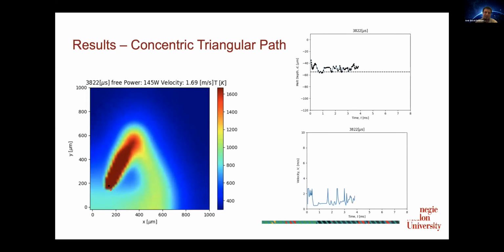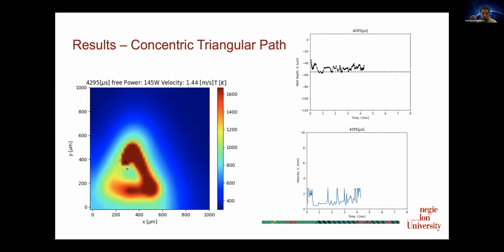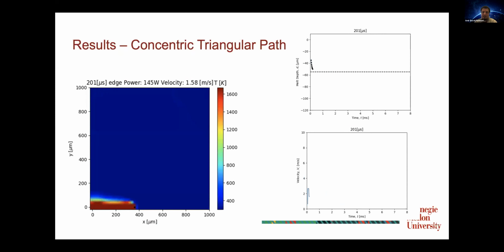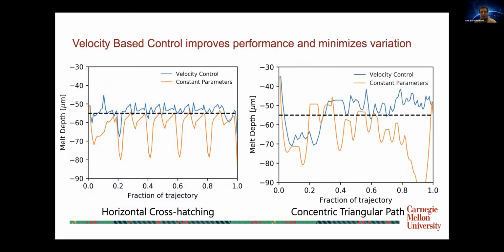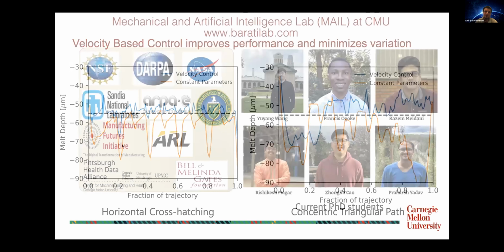Especially in the middle, there's a huge accumulation of heat. So turning off that laser is very important. Here you can see there is a huge difference between when you are controlling the velocity and if you are using a constant control strategy without deep reinforcement learning. The melt pool is essentially very well kept when you are doing the control. But if you don't do the control, you can see a huge variation in the melt depths of the pool.